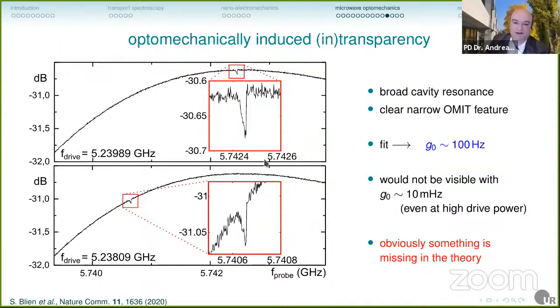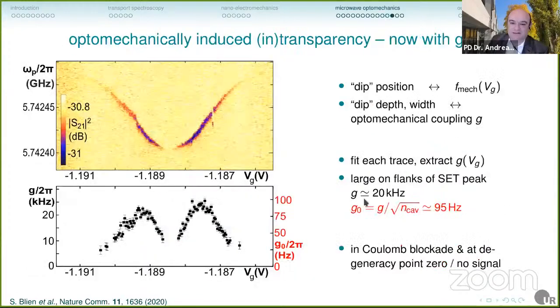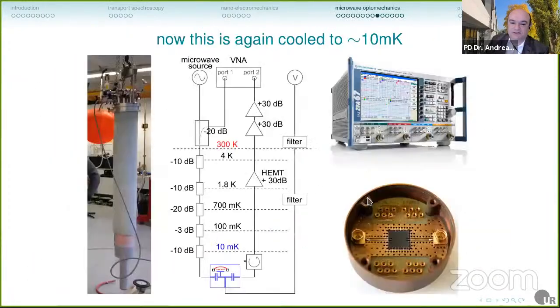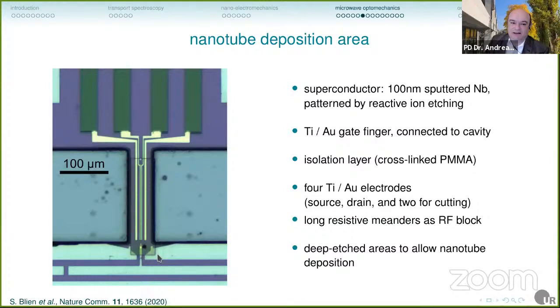Yeah, we made resonator chips without these carbon nanotube transfer areas that had a microwave cavity Q of 200,000 or so. But the limitation is not so much the nanotube itself, but, let me show you, that these coupling electrodes here, of course, also couple energy out of the microwave resonator. And at the moment, we've been working a lot with Sonnet to optimize this so that we don't lose so much of the microwave signal over the DC lines.